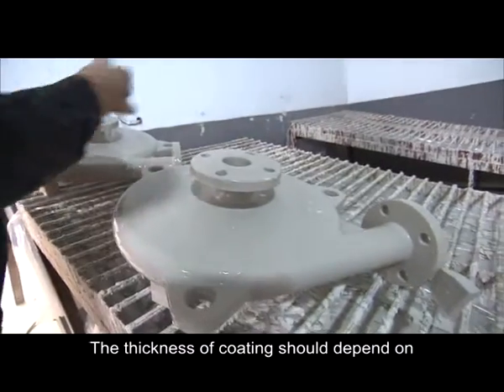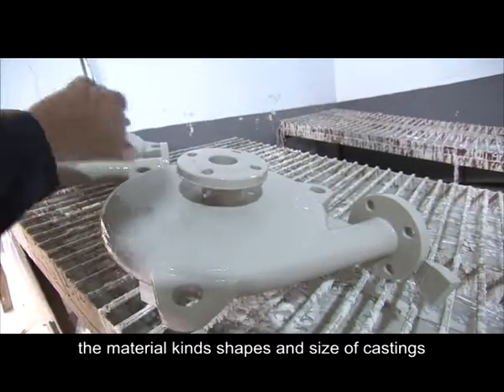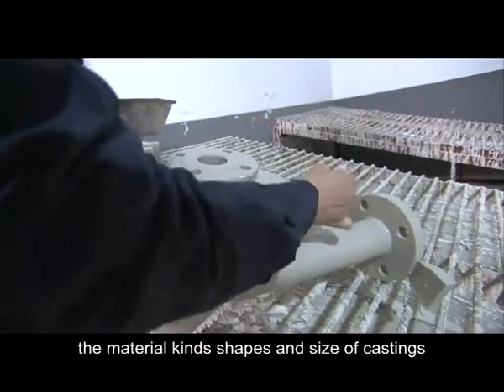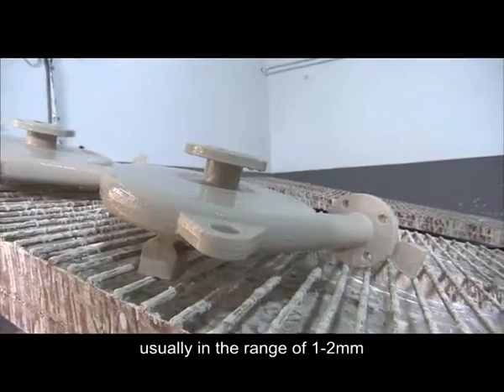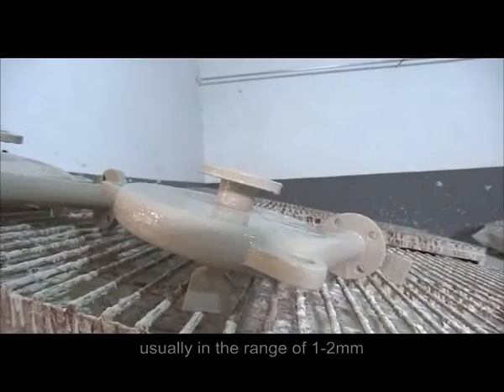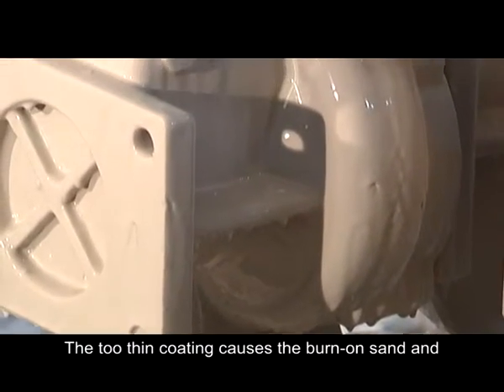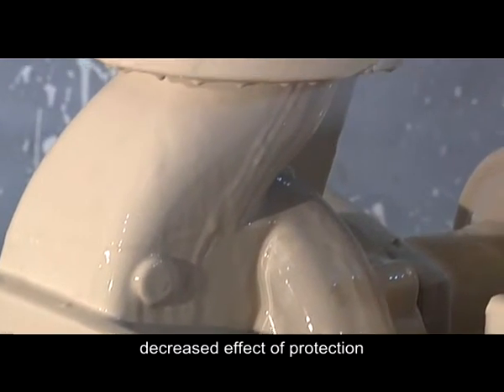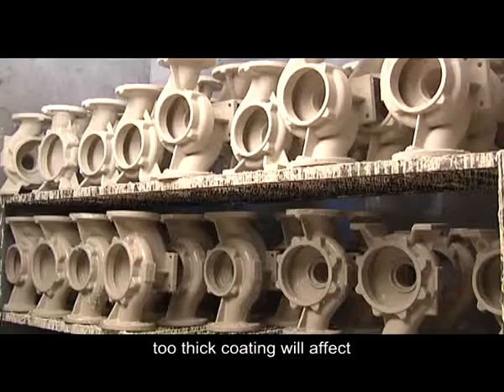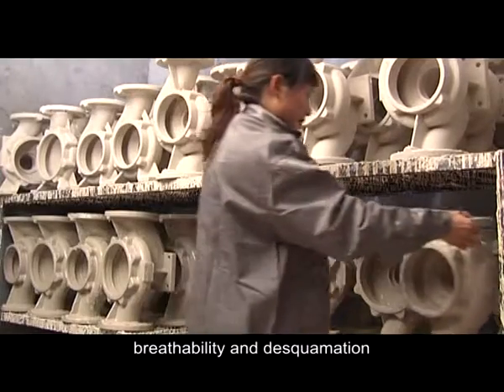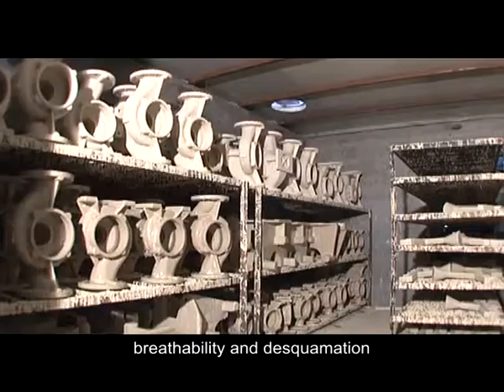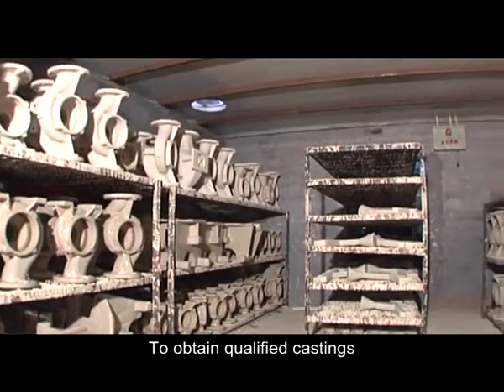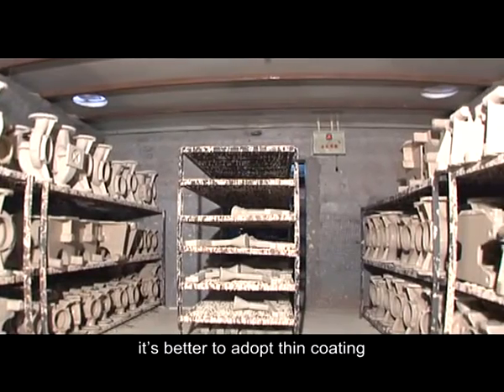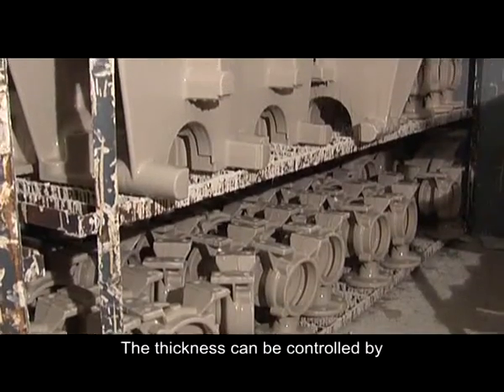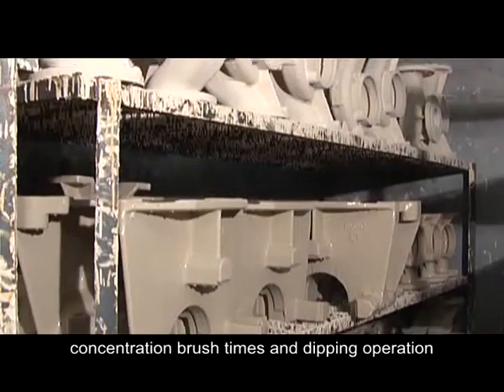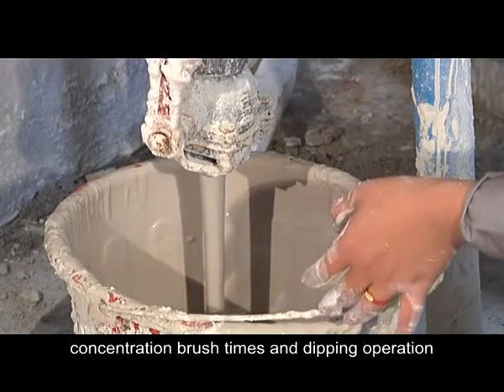The thickness of a coating should depend on the material, kind, shapes and size of castings, usually in the range of 1 to 2 mm. Too thin a coating causes burn-on sand and decreases the protective effect. Too thick a coating will affect breathability and cause desquamation. To obtain qualified castings, it's better to adopt thin coating. The thickness can be controlled by concentration, brush times, and dipping operation.